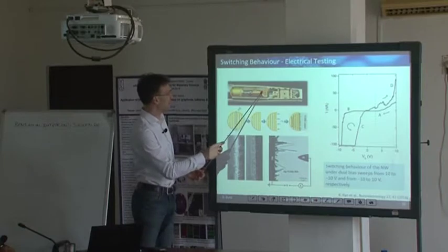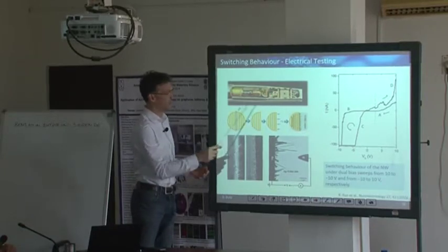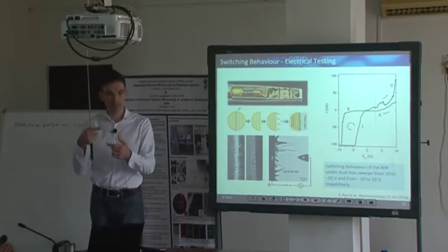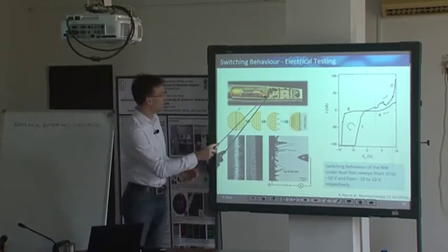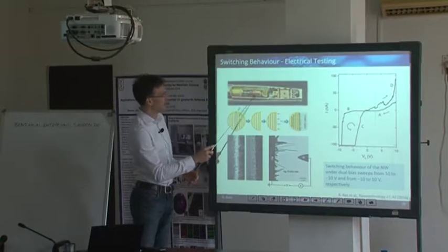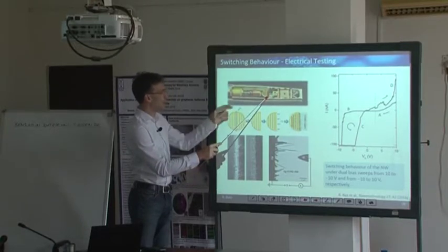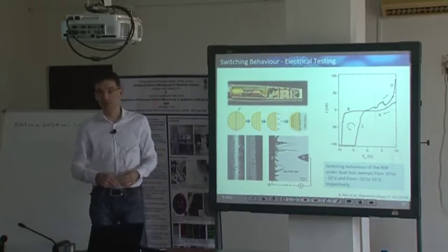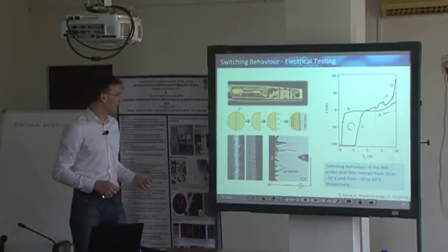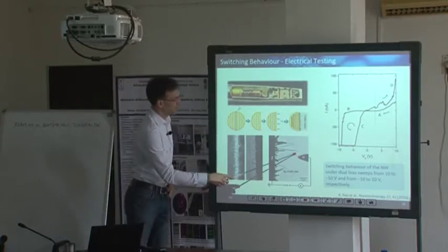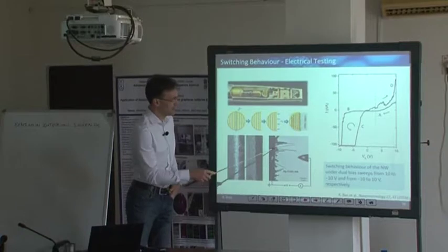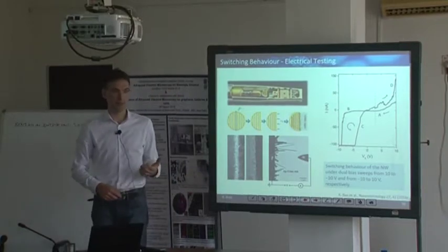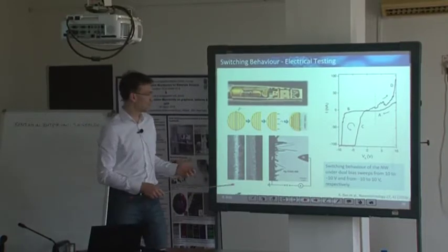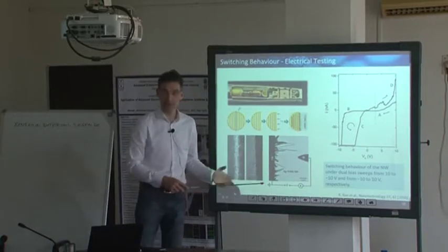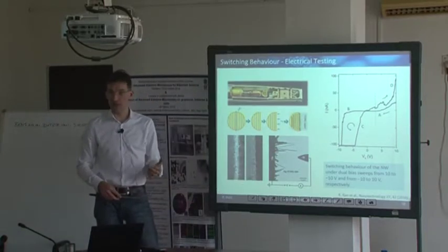So in this particular case, the TEM sample is mounted on the left-hand side, and on the right-hand side you just have a metal tip installed, and you can manipulate your sample and move your sample and contact very, very locally. This is one example where we measured the switching of TCNQ nanowires, so this is more an organic molecule, and by introducing currents up to a certain field strength, you will see that the resistivity changes.